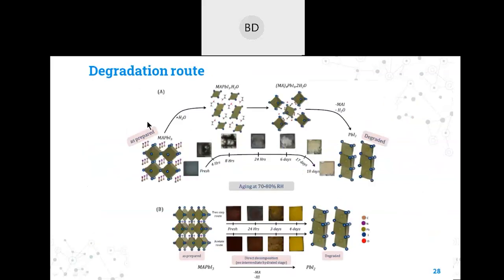If you see the degradation route here, if we take the lead iodide route, under the exposure of a small amount of H2O, it goes through a monohydrate phase formation. This monohydrate phase formation can be seen from this film as well. The white part in this film shows some kind of hydration itself. And after some time of aging, around 24 hours or so, this monohydrate phase, when it has a high amount of H2O, starts converting into the dihydrate phase. And after some time, when the water molecules or MAI are evaporated, it converts into PbI2. So this yellow portion in this film shows the PbI2, which is the color of lead iodide.